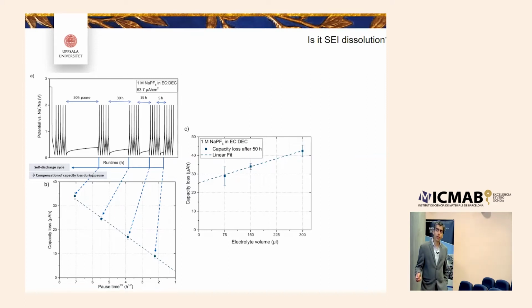What we do basically is cycle, pause, and then see how much capacity is lost during this pause. What we learn here is that this capacity loss is dependent on the square root of time. We can also see that this capacity loss is very much dependent on the electrolyte volume—there's a linear relation between that.